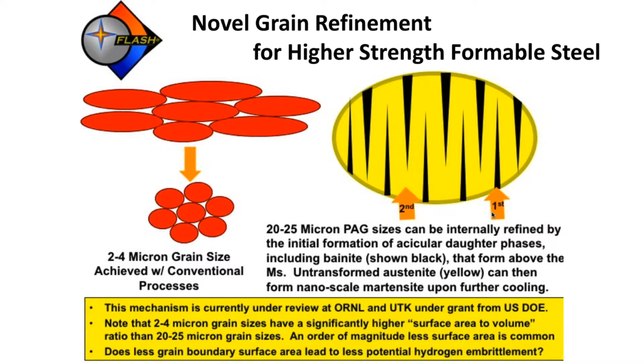This is done in about 80 milliseconds, and for maybe another 100 milliseconds, untransformed austenite remains in those yellow regions. Once we start hitting the martensite start temperatures, these nano-refined regions, represented by the yellow untransformed austenite, then start to form martensite. So we've now got a 20 to 25 micron grain of a mixed microstructure of bainite, which greatly refines the martensite as it's being formed, which we believe is what leads to the 7 to 10% higher strength.